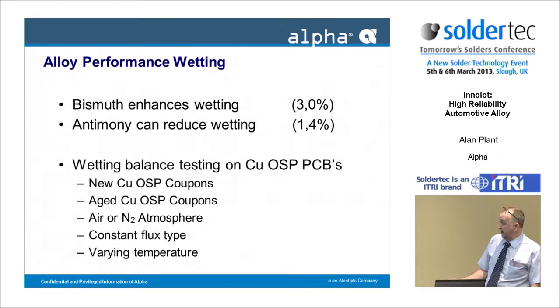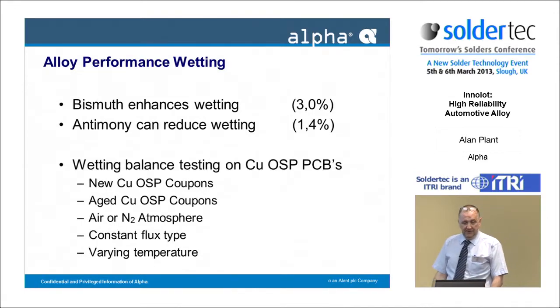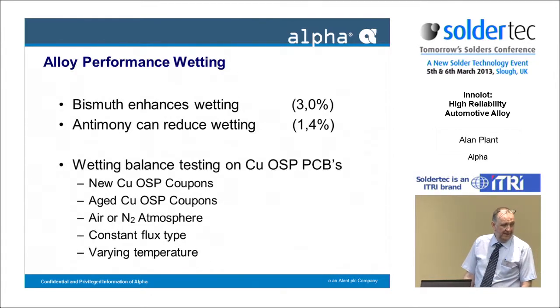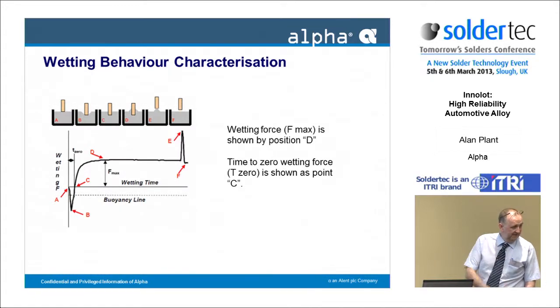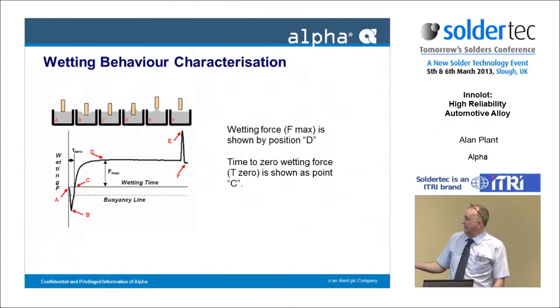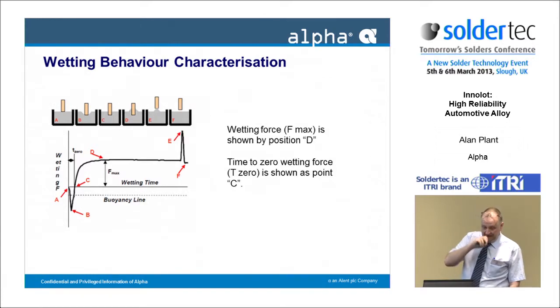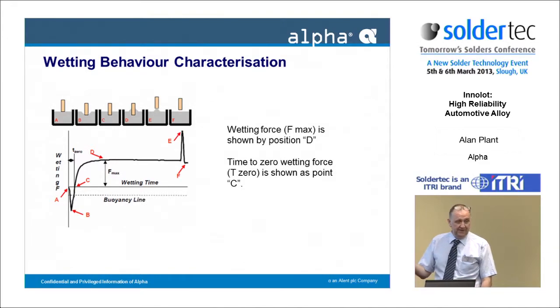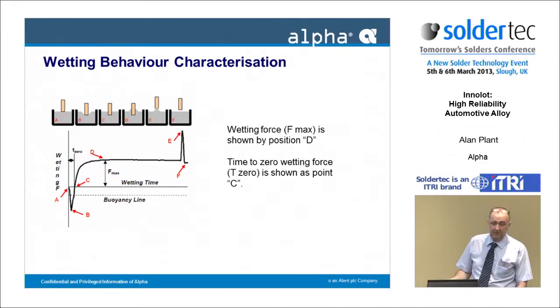So really what we were looking at is varying the temperature on a solderable finish, with the specific aim to see how low we could make it wet, and was it wettable at a lower temperature than the standard SAC alloy. And as you were trying to explain before, this point, this time to buoyancy, this neutral line, when you first put a piece of metal, whether it be a wire, a piece of laminate, into a liquid bath, but these tests often use globules and surface mount type configurations. But it's the same thing, when you first put it in, it's cold, the thing is buoyant.